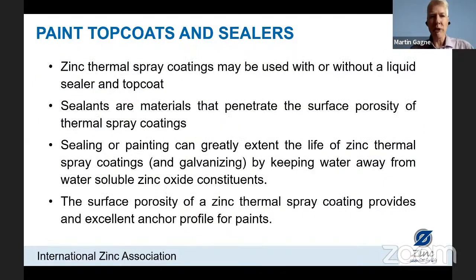So we've talked about a duplex coating, putting a paint top coat on top of thermal spray zinc. The sealant really fills the porosity at the surface, and is also sometimes called the tie coat because it aids for the paint adherence, although the rough surface of the thermal spray zinc is an excellent anchor for any paint coating. So again, this will extend the life of the thermal spray zinc coating by adding another barrier coating. So the paint will protect the zinc, but now the zinc will also protect the paint if there is, again, a scratch or a hole through a duplex coating.